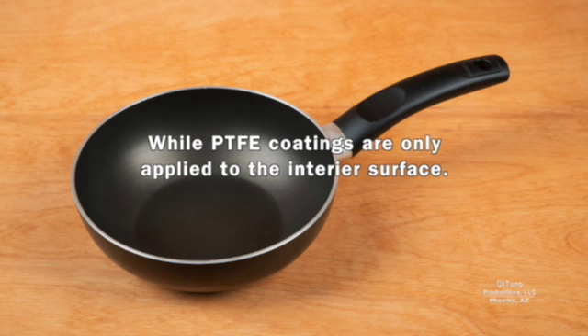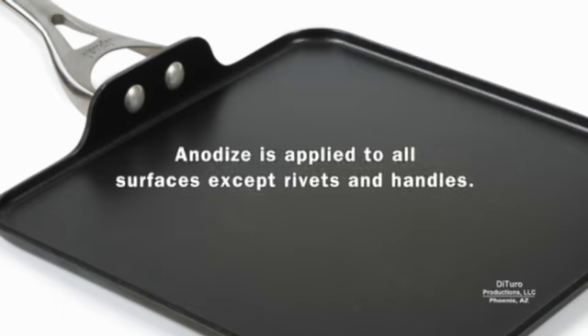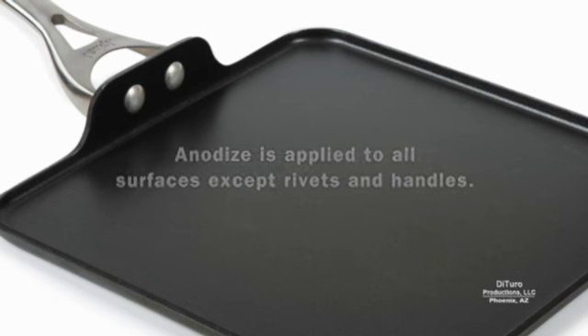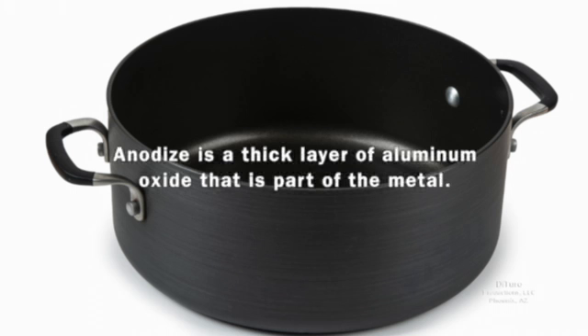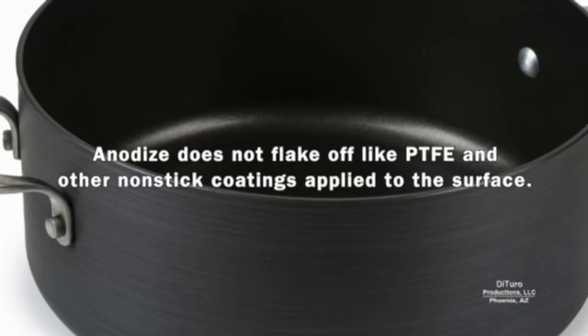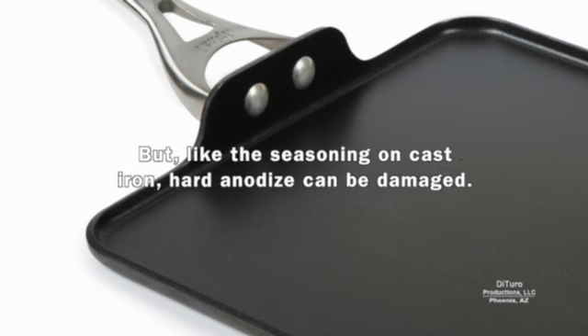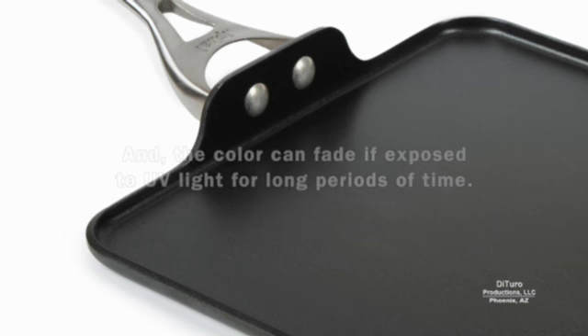While PTFE coatings are only applied to the interior surface, Anodize is applied to all surfaces except rivets and handles. Anodize is a thick layer of aluminum oxide that is part of the metal. Anodize does not flake off like PTFE and other nonstick coatings applied to the surface. But like the seasoning on cast iron, hard anodized can be damaged. And the color can fade if exposed to UV light for long periods of time.